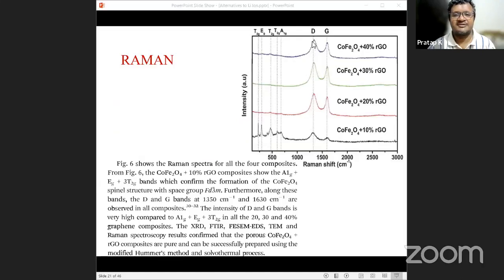So this is our Raman, and generally, if you have RGO, it is confirmed by D and G peaks in the Raman band. So here are the D and G peaks. So the D peak is having the highest intensity, and the G peak, these are the defect peaks. So the formation of RGO is confirmed here, and this is clearly showing that porous cobalt ferrite with RGO is successfully prepared.